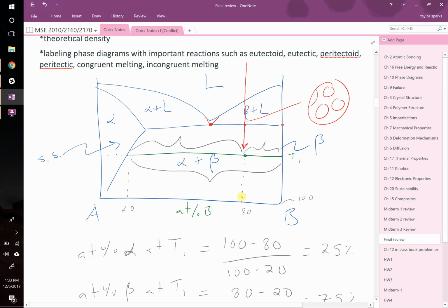If you were then down here and I said draw the microstructure, well, it's no longer 25-75. It's probably like 20-80%. But still, you will have some pro-eutectic phase. You'll have some pro-eutectic beta. Everywhere else is going to be lamellar structure, a mixture of alpha and beta. And you would label the compositions, the amounts, using the lever rule.